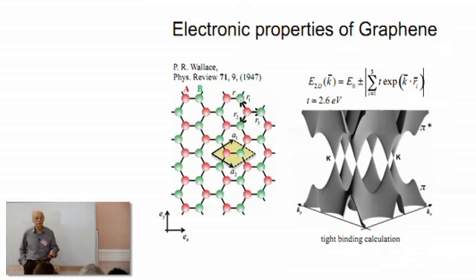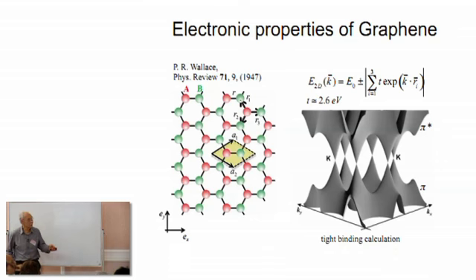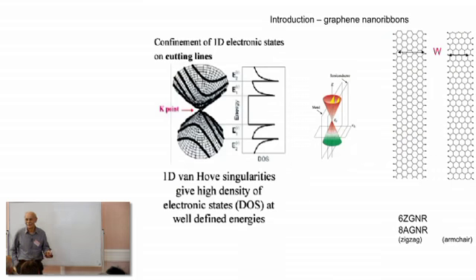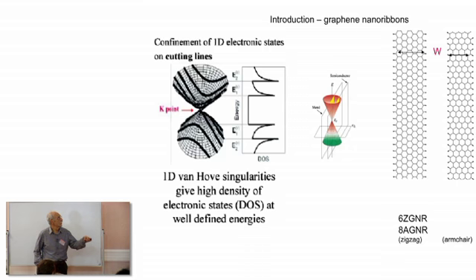Now many people check the structure by more accurate methods, and all of them obtained the same picture, because this structure is not destroyed under environment. And when we cut graphene, you can see here the simple nanoribbon, with length and width.